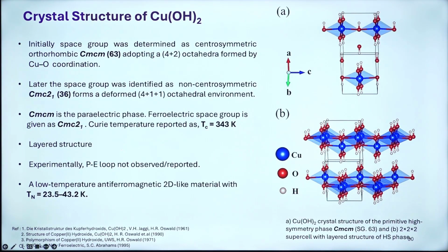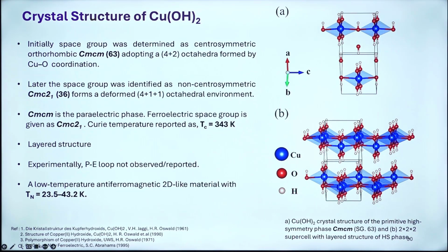Yeah, so this is the experimental picture. It is reported that at low temperature it orders antiferromagnetically, like a 2D material, but the Néel temperature is very low, 23.5 or 40 to 43 K; there were reports ranging in this paper. Initially the space group was determined to be centrosymmetric. With Cmcm centrosymmetry, we can rule out any possibility of the system getting polarized. Later the space group was identified as non-centrosymmetric Cmc21, forming a deformed 4+1+1 octahedral environment. Cmcm is the paraelectric phase, the ferroelectric space group is Cmc21, and the Curie temperature for this ferroelectric transformation is around or above room temperature, 343 K. This is a layered system, and the experimental PE loop is not reported.